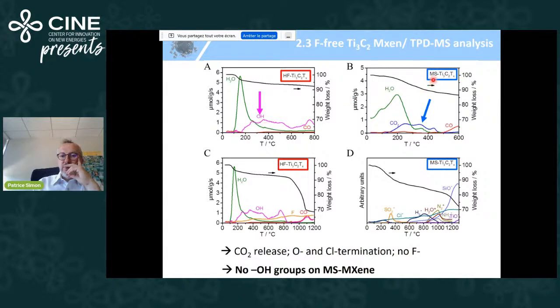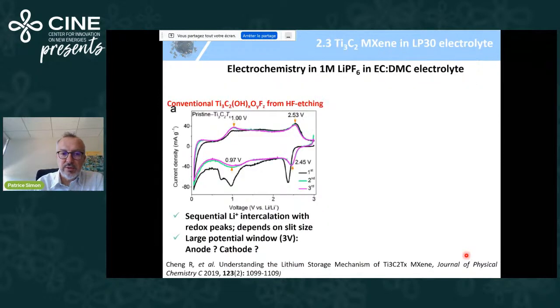Here, this is our molten salt MXene. We still have water. However, there is no more OH. We have CO2, meaning that we oxidize a little bit of carbon. And obviously, if you go to the full spectra until 1200 degrees Celsius, you see that we have some chlorine and so on evolving from the surface. This is a degradation of the MXene. And here you have fluorine because it's an HF MXene. So the message is that there are no OH groups and no fluorine groups on the MXene. It's only oxygen and chlorine termination.